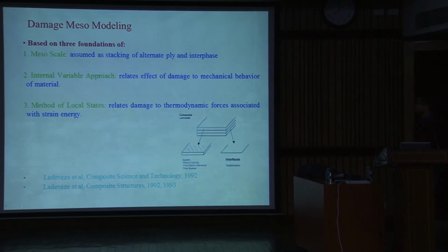Then the method of local states. So, it relates the damage to the thermodynamic forces associated with the strain energy. Okay. So, this thermodynamic force is nothing but the dual of this damage indicator. When you have this damage indicator and thermodynamic force together, it will give you back the energy, or strain energy, or the free energy.